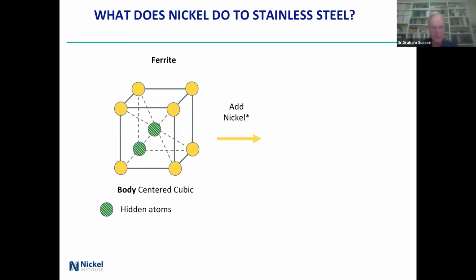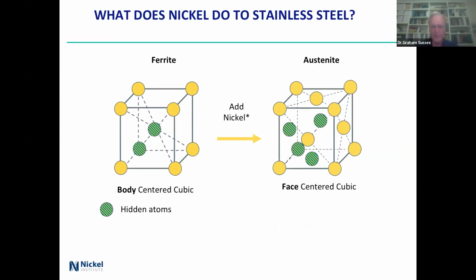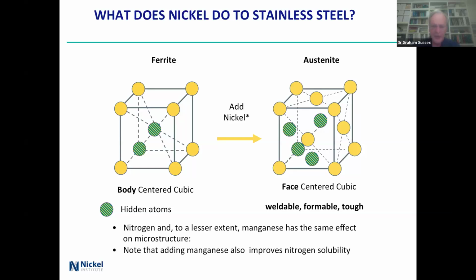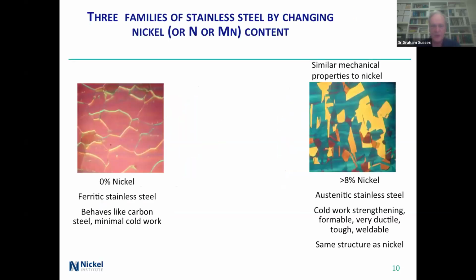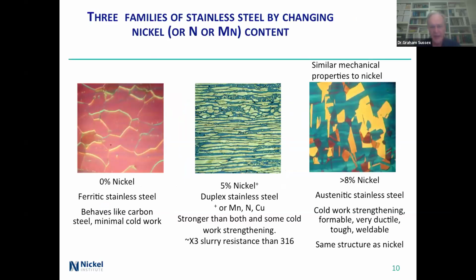Body-centered cubic ferrite, add nickel, and you wind up with face-centered cubic, weldable, formable, tough, and nitrogen is one of the things that help with making that structure. And if you add manganese, I've already said, it improves the nitrogen solubility. So that's ferritic on the edge. Add some nickel, but not a lot, and you get the duplexes, and I'll talk about that picture in a bit of time. And of course, if you go the whole way, then you get the austenitics across the far side.